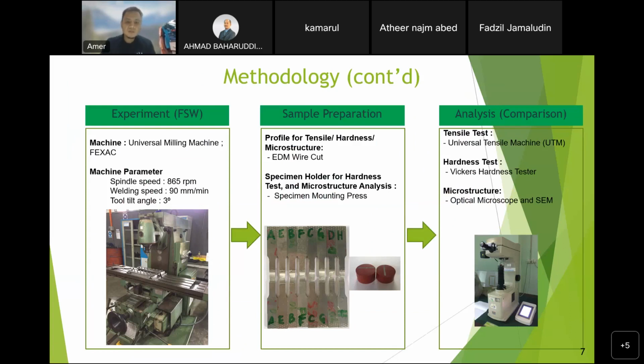For the sample preparation for the tensile, hardness, and microstructure, I'm using EDM wire cut to cut the specimen profile. For holding the specimen, I'm using a specimen mounting press. This is for the microstructure and the hardness test.